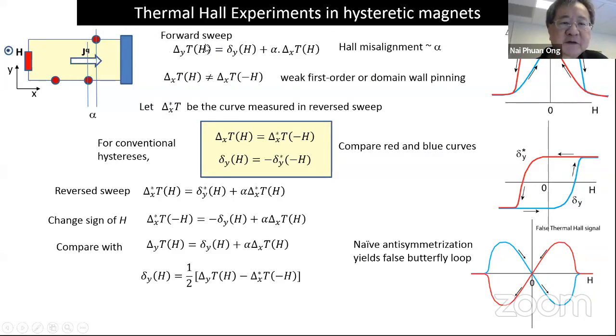All right, so let me explain what you observe experimentally. So this is what you measure physically, what you observe, right? That's the temperature difference. Remember, I said, do not use a thermocouple. Thermocouples are useless at this temperature range, and they tend to have very large field dependencies that are a nuisance. Totally unreliable. And this is the intrinsic signal that you're going to feed into your resistivity matrix, right? This is the intrinsic signal that you hope to disentangle. And here's the contamination due to misalignment alpha. And it becomes a problem when it's not only hysteretic, but it has memory, right? And here's a sketch of what that looks like.